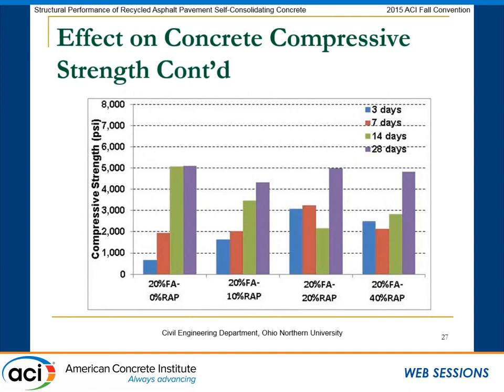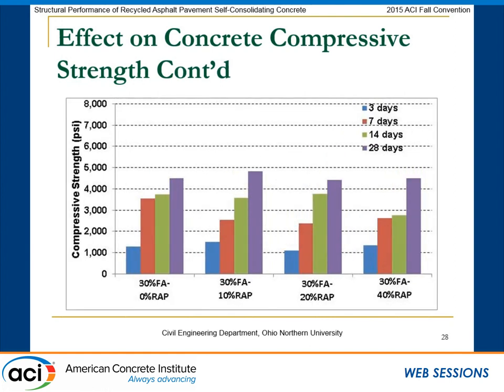Remember, it was higher than 5,000 PSI. But then as the RAP, here with the 10%, you have this reduction and then an increase for 20%, and then it decreases again for 40% RAP. For 30% fly ash, it reduces further than the 20%. And then when the 10% was introduced, you had a higher strength, and for 20% RAP, you had a smaller strength, and then 40% RAP, you had smaller.